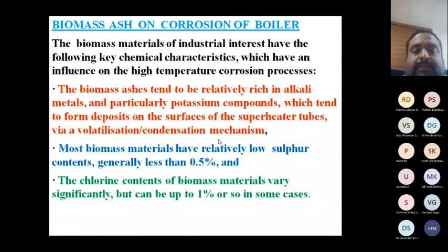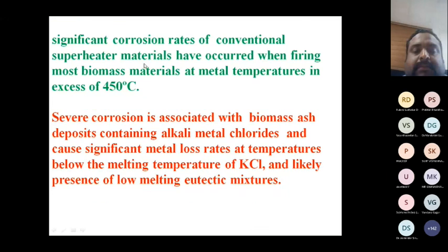Biomass materials have the following key chemical characteristics which influence the high temperature corrosion process. Biomasses tend to be relatively rich in alkali metals, particularly potassium compounds. Then they have low sulfur and a significant amount of chlorine. So potassium and chlorine play a vital role in high temperature corrosion. Significant corrosion of conventional superheater materials has occurred when firing most biomass at metal temperatures in excess of 450 degrees. So there is severe corrosion associated with biomass ash deposits containing alkali metal chloride. So if you have potassium and chlorine, potassium chloride, you have a significant amount of superheater corrosion.